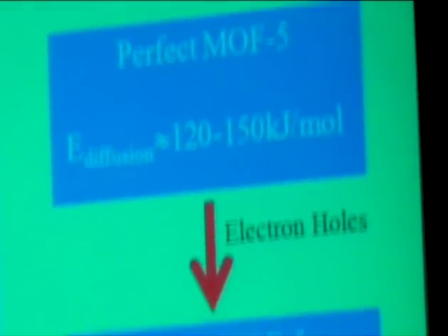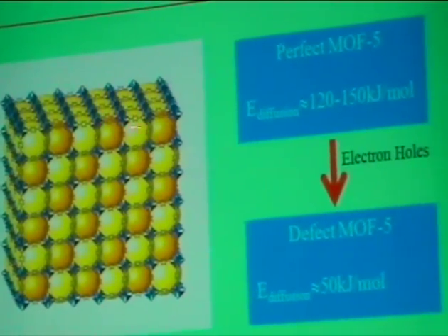So how can they do this? They did calculate this. If you have some electron hole, then your activation energy can be reduced to 50 kilojoule per mole. With 50 kilojoule per mole less, you have a chance to move at room temperature. So how can you get an electron hole? Actually, you can see this inorganic cluster, that's zinc oxide. If some zinc is lost, then you can get an electron hole. So when you synthesize this one, you can get lots of defects. That means some clusters are not perfect. They lost some zinc. If you lose zinc, they can form an electron hole. If you form an electron hole, then you can reduce your activation energy very much. Only 1/3 of the activation energy is needed. So if you do this, then you can move.